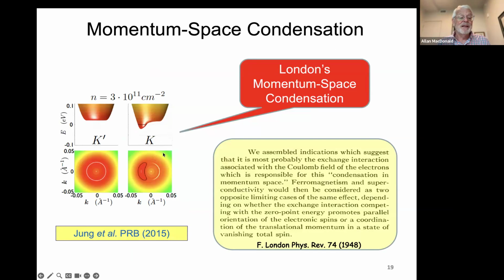There is a tendency in mean field theory, and I think also for quenched order described by mean field theory or fluctuating order, which we can't necessarily capture in a mean field theory, to favor occupying states that are close together in momentum space, because those states have the strongest Coulomb matrix element, and there's most energy to gain from correlations.